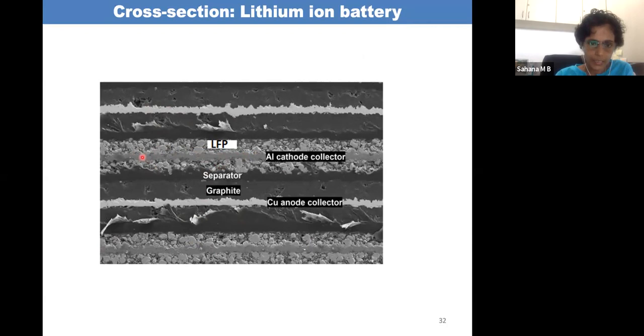As I told earlier, if you see a particle here during intercalation or deintercalation, that is during either charging or discharging of the cell, during charging the electron from this particle has to travel all through this 100 micrometer thickness and go to the current collector. During the discharging process, the electron from the current collector, which comes from the outside circuit, has to travel all the way to this particle. So the conductivity of this whole electrode should be very good.